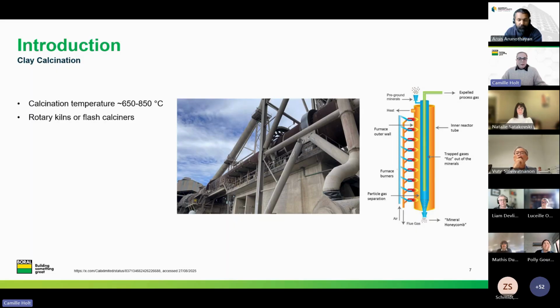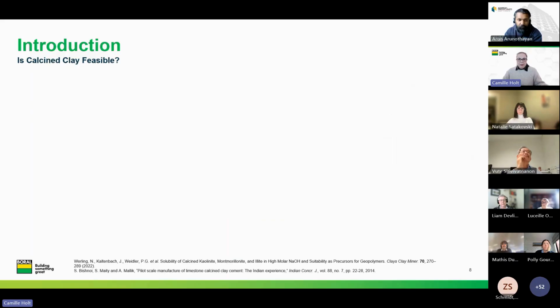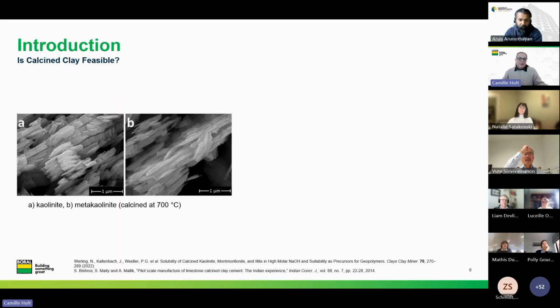So what happens when we use calcined clay as a cement replacement? Without trying to steal too much of Paul's thunder, when you compare calcined clay to fly ash and slag, the chemistry is highly similar. All three materials are reactive aluminosilicates, which will react in the presence of hydroxides to form the same hydration products. But one notable difference is in the particle shapes.